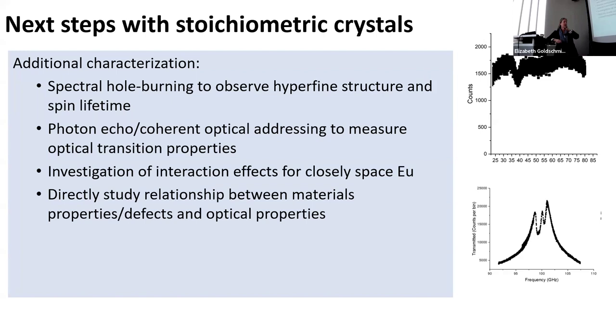And then, if anyone here is a material scientist, we're trying to figure out ways to directly study the role of defects, materials properties, and the optical properties that we care about. But the defect rate that we have in our crystals is pretty low. We do X-ray diffraction, it looks fine. So trying to do very careful measurements of relatively low defect rates is something we're interested in. We're looking for methods to do that. We have some ideas. Once the Advanced Photon Source at Argonne is back up and running, we have more ideas. That's something we really want to do to refine our growth and reduce these inhomogeneous line widths.